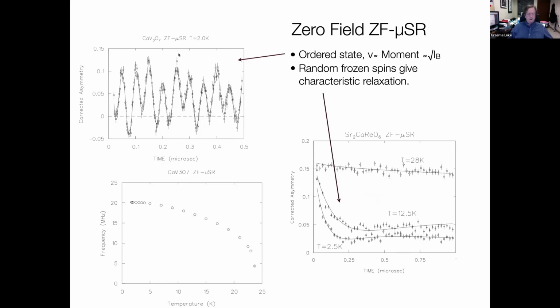If we have a material, here's an oxide, calcium vanadium oxide, and this is measured in zero magnetic field, and we see beautiful precession of the muon spin polarization. And that's because this material is an antiferromagnet, and by measuring the temperature dependence of the precession frequencies in this particular material, there are 2 sites for the muon, so there's 2 frequencies. Here I'm showing you the temperature dependence of one of these frequencies, and that's just an order parameter for the magnetic order. It would correspond to the square root of a Bragg peak intensity in neutron scattering.